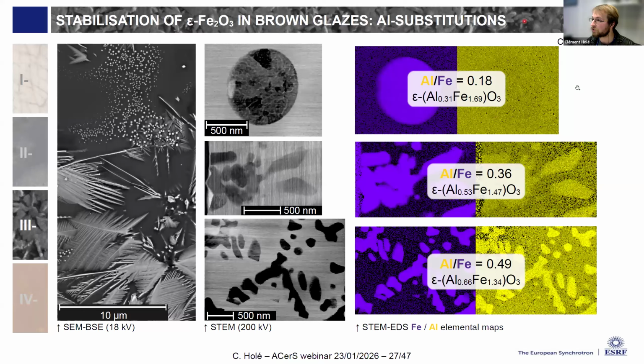And we could actually quantify this and see that indeed we have a sharp increase of the aluminum to iron ratio between the, let's say, nuclei of dendrites and the fully fledged dendrites. And what's very interesting is that the mixed aluminum and iron oxide with the same structure as iron epsilon oxide exists.